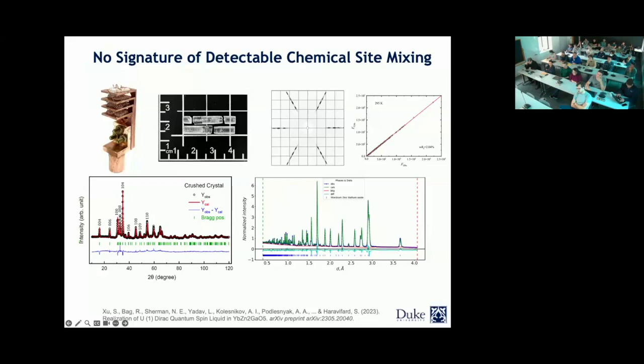So it actually shows that the chemical disorder is not favorable in this particular case. However, when you think about it, the zinc 2+ and gallium 3+ have the same electronic configuration. So in the eye of X-ray, they are practically the same, because X-rays look at the electrons, right? In that case, one would say that the cross sections for the gallium and the zinc are the same. So maybe you're just blind to the chemical disorder when you look at it with X-rays.